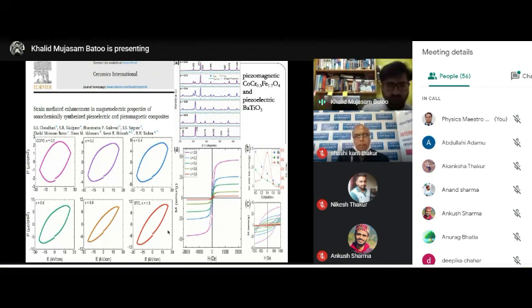Once we started doping, we saw the loop structure changing from 0-0 composition to 1, that's 100%. The loop is shifting, becoming more elliptical and elongated, and the value is increasing from 3 to almost 12. So this is getting better.